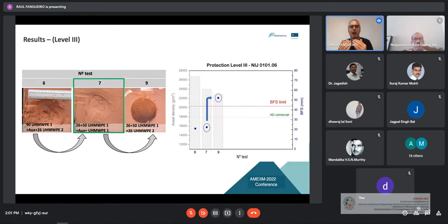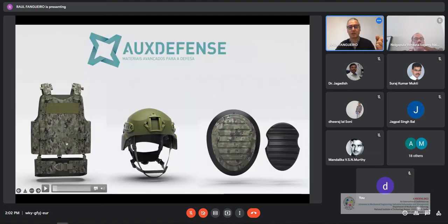And with the auxetic material, we are able to distribute better along the surface of the back material in order to not lead to a deformation through the thickness of this material. In this graph, you can see that for these samples the backface signature is in these two points, so we are around 20 millimeters. But when removing this auxetic layer, you may see that we are beyond the limit for the backface signature in terms of the standard. So it means that the auxetic material is playing a very important role here in the solution.